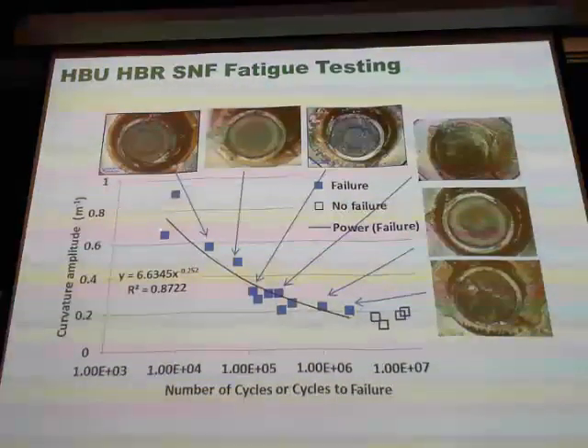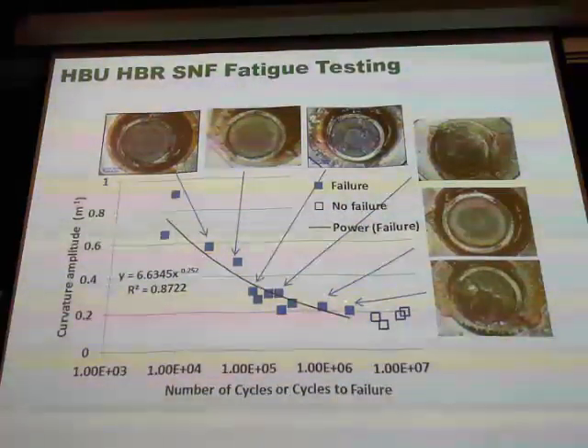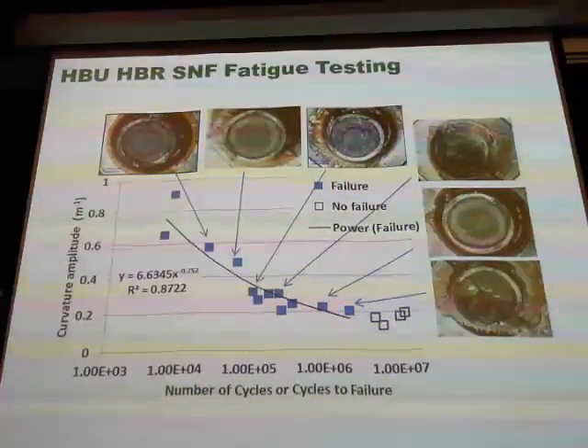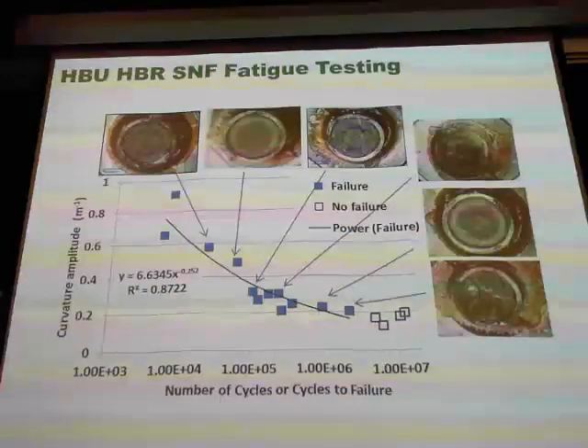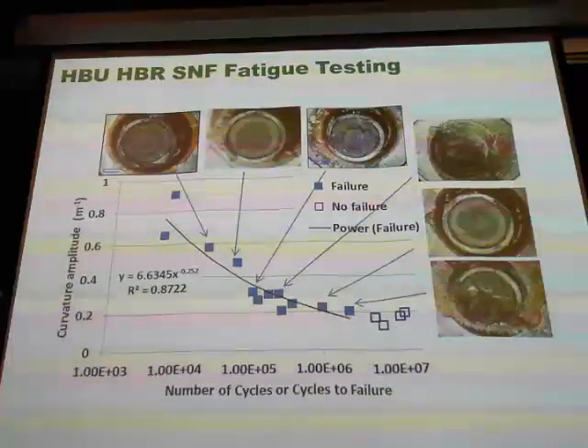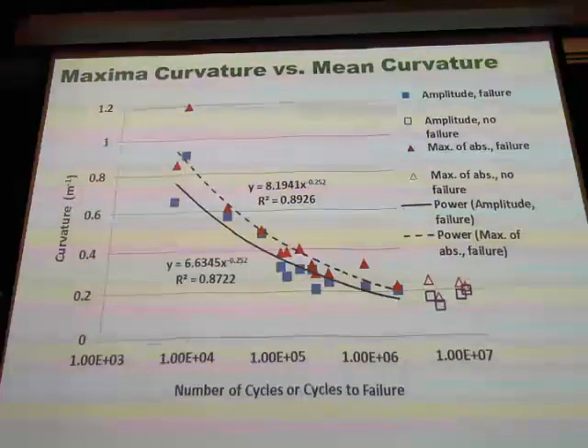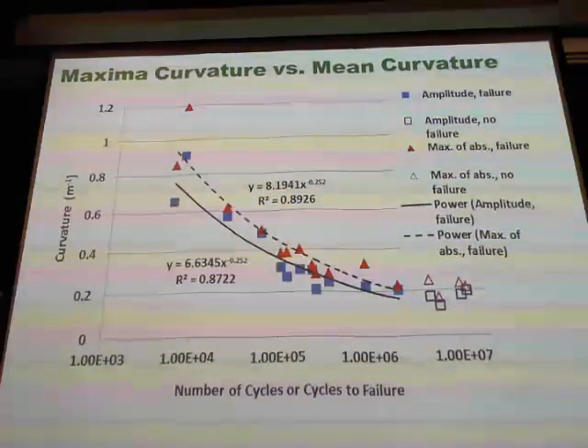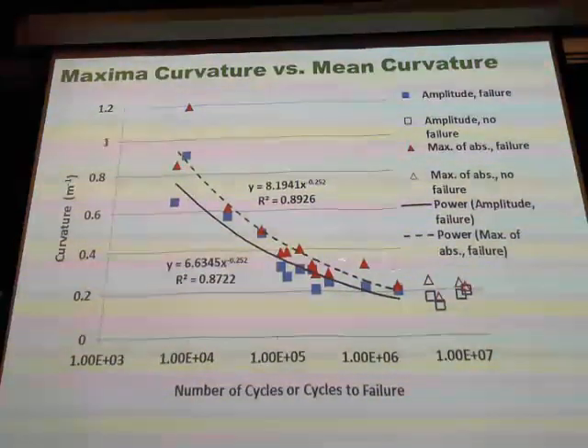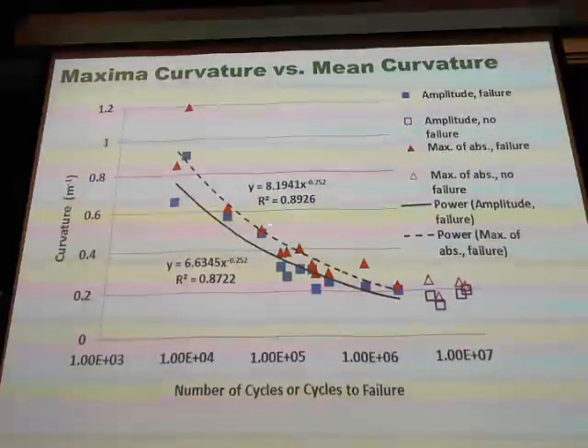No warning. And this is the S-N curve data we collected. It's still consistent. Almost everyone failed at the pellet-pellet interface, at the stress concentration. As I mentioned earlier, the maximum clad curvature and the compressive clad curvature are different. The maximum curvature is higher. But this is the mean curve, called the curvature amplitude. You can see the two are different.